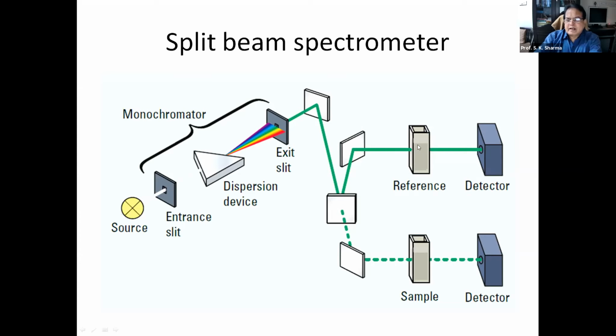So the zero baseline is recorded by putting the same solvent in both the cuvettes. So first we record a zero spectrum. We put either water in both samples or ethanol in both samples or benzene in both samples, so that the solvent effect is not there. The effect our detector records is the effect of those particles that are available only in the sample cuvette. Okay.